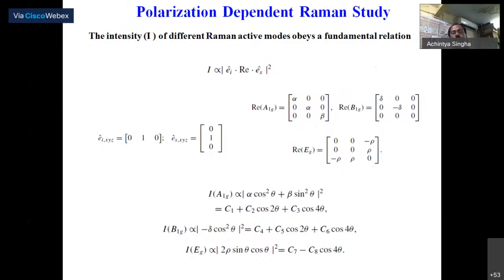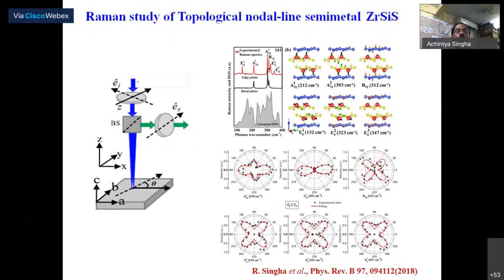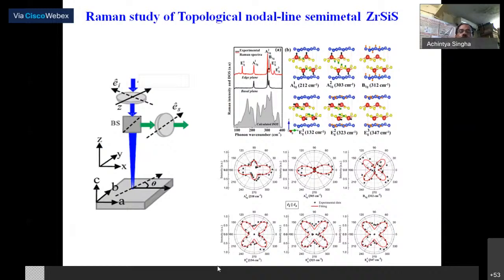Go next. So here is an example of this ZrSiS crystal, which is actually a topological semi-metal material. You can see the polar plots on the right side and the bottom figure. Different modes show different symmetrical behavior. The Raman measured intensity of this mode, the scatter points, is very consistent with the calculated result. So in this way you can check the symmetry of the system.